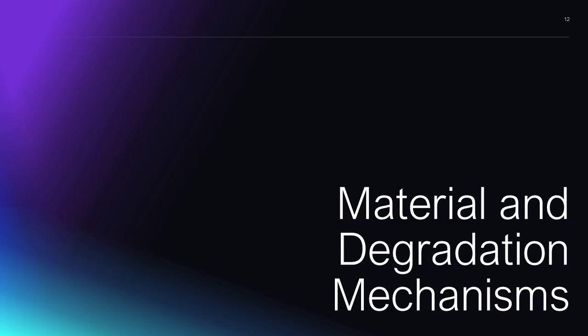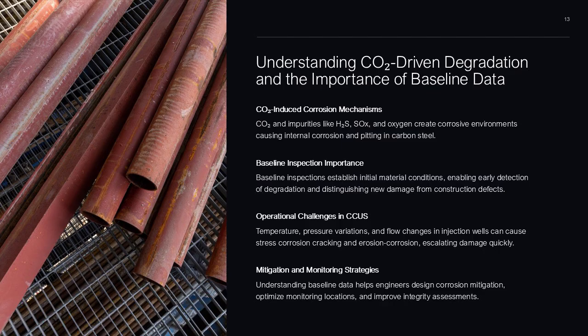Understanding CO2-driven degradation and the importance of baseline data. Material integrity in CCUS facilities is influenced by unique degradation mechanisms driven by CO2 and its impurities. Carbon steel in the presence of water and CO2 forms carbonic acid, which accelerates internal corrosion. Trace components like H2S or SOx can form highly corrosive environments, while oxygen can destabilize protective films, and water dropout increases localized pitting. In injection wells, temperature and pressure variations may cause stress corrosion cracking or thermal fatigue.